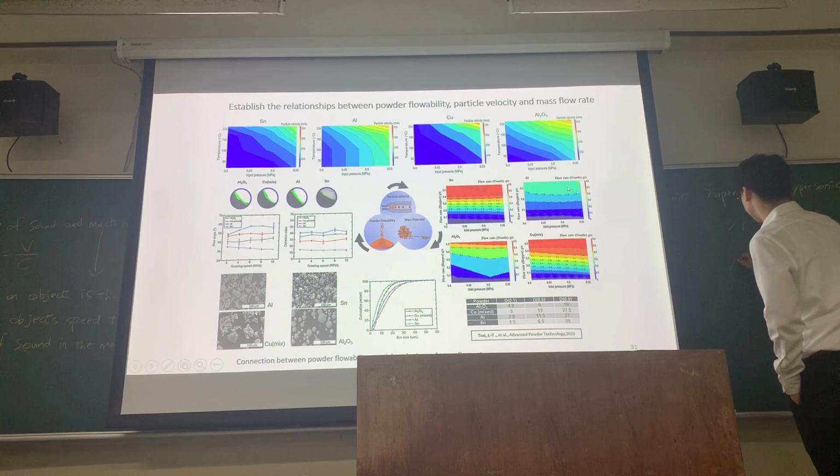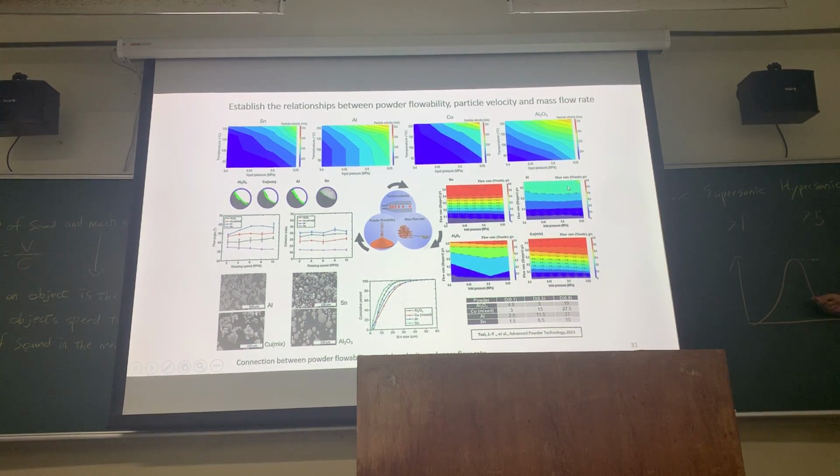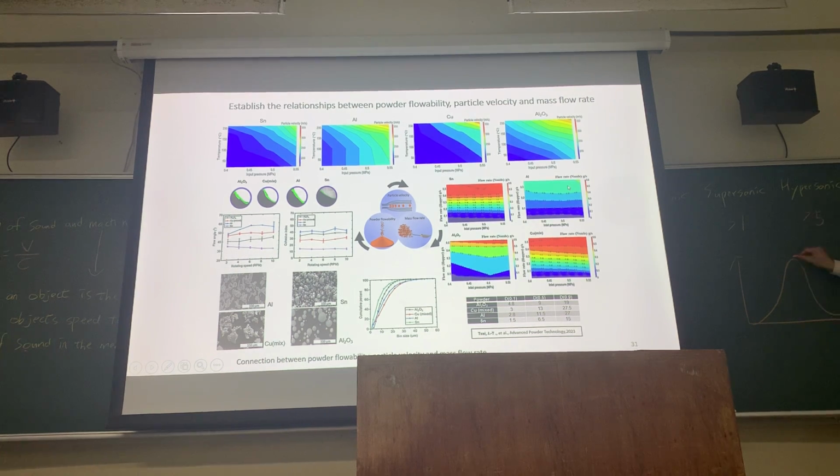So you have something like this, you have a distribution, right? A normal distribution, right? So 50% is the middle, then 10% is here, and then 90% here, right? So you're reading. So when I plot this, you assume this is the distribution. But sometimes powder isn't like this. A lot of times you'll see powder that has a camel peak like this.